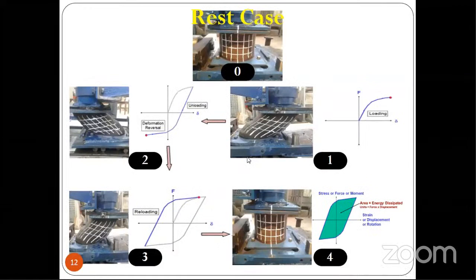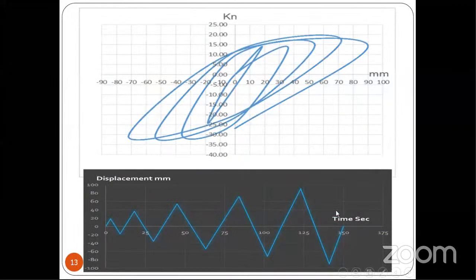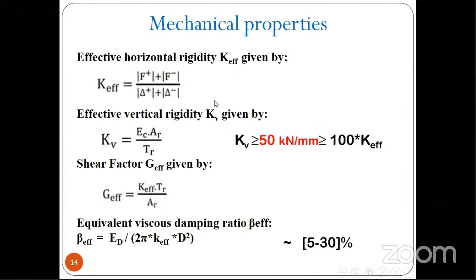The hysteresis loop created by cyclic load is loaded here. Then we unload, and finally we reload again. This green area expresses the amount of energy dissipated. This is the experimental result of our isolator. And we can find the mechanical properties by these two equations, where the vertical rigidity should be greater than 50 kilonewton per millimeter, and the damping ratio around between 5 and 30% as we saw before.